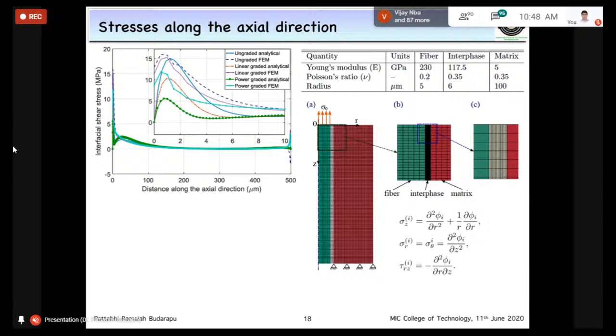That's where the stress peaks are going to occur across the interface, and because of these peak stresses, it creates the interfacial debonding. So the region very close to the fiber, within the interface region, and very close to the matrix is where the stress variation is shown. You can see a sharp drop, let's say from some 15 megapascals to maybe 1 megapascal within a distance of 4 microns.